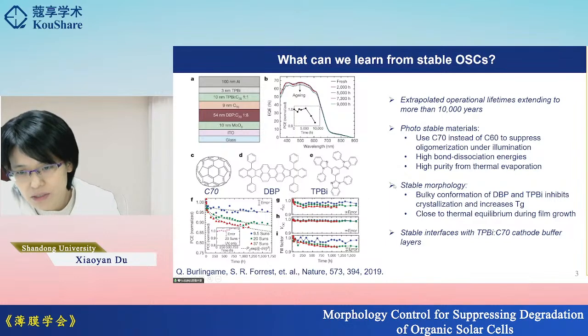About the morphology, this kind of material has bulky conformation. This will be helpful to inhibit crystallization and increase Tg. And due to the thermal evaporation process, the molecules are also able to form a stable mixing close to the thermal equilibrium state. Of course, here we see the interfaces. It's also a little bit more complex than what we use in most of the solution processed organic solar cells.